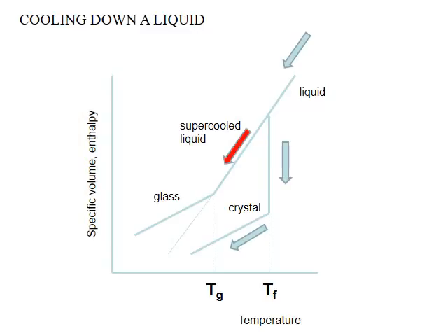In the plot, by cooling the supercooled liquid, viscosity increases. When viscosity is around 10 to the 12 Pascal second, the material starts to behave like a solid. This is the transition from the viscous supercooled liquid to the solid. In this case, an amorphous solid, a glass. We call this temperature the glass transition temperature. Cooling further, the volume will decrease at a rate similar to the crystal.